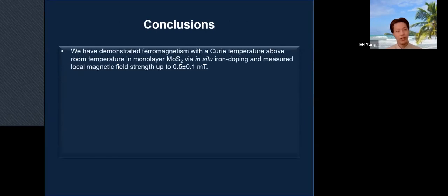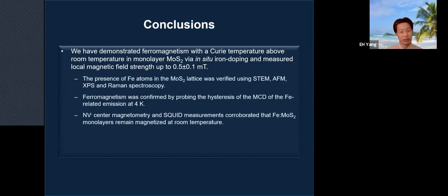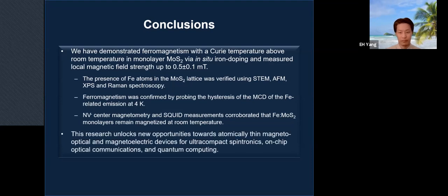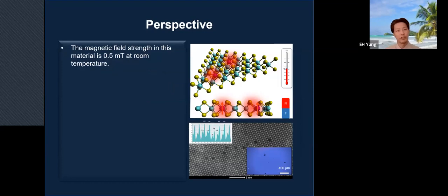Now, in conclusion, we have demonstrated ferromagnetism with a Curie temperature above room temperature in monolayer MoS2, molybdenum disulfide, here. We used in situ doping, and we also measured local magnetic field strengths up to 0.5 millitesla. We confirmed the substitutional doping using STEM, AFM, XPS, and Raman spectroscopy. And ferromagnetism was also measured using MCD, nitrogen vacancy sensor, and SQUID measurements, which were further corroborated using DFT simulation.